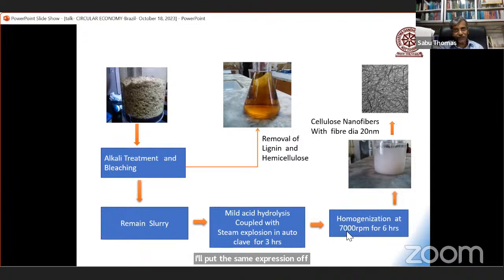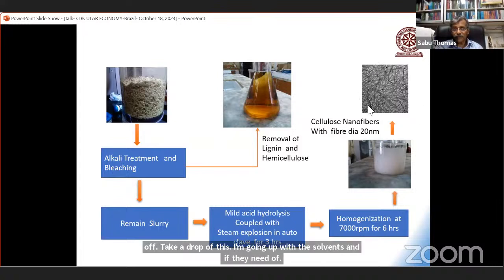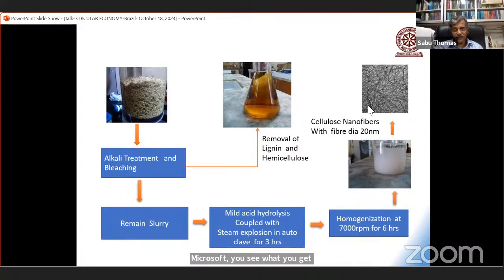Then we go for a homogenization process, around 7,000 RPM for 6 hours. Then we get a suspension of nanocellulose in water. If you take a drop of this and evaporate the solvents under the grid of an electron microscope, you see what you get: a beautifully entangled network of nanocellulose.